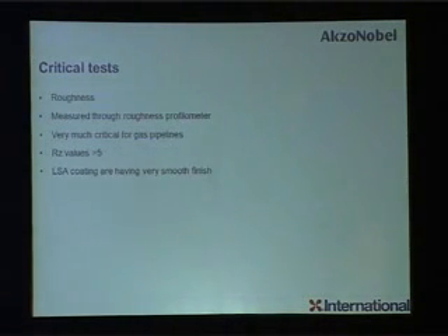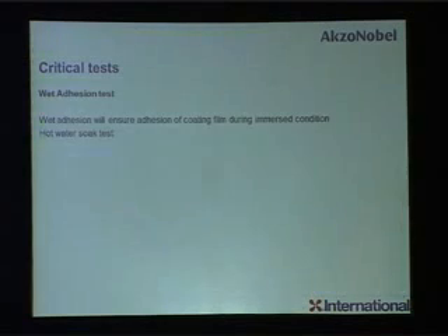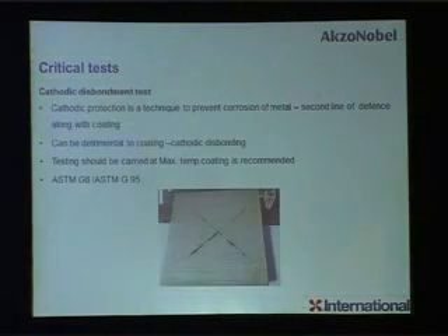Then other than this, if you go to pipeline sites or pipeline coating manufacturers, this test is very important. It's called the roughness test, mainly for gas pipeline internal coating industries, because the roughness, the smoothness of the pipeline coating, has a direct relationship with the flow of the gas during transportation. So different customers have different specs. We have seen even a spec of less than 5 for some critical European customers. Then the wet adhesion test. And the cathodic disbondment test, I think we have already covered in the last few presentations, so I will not go into this.